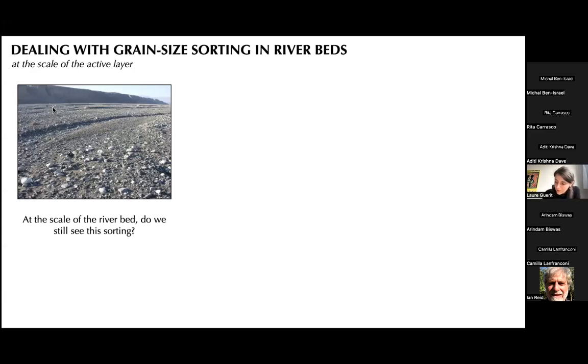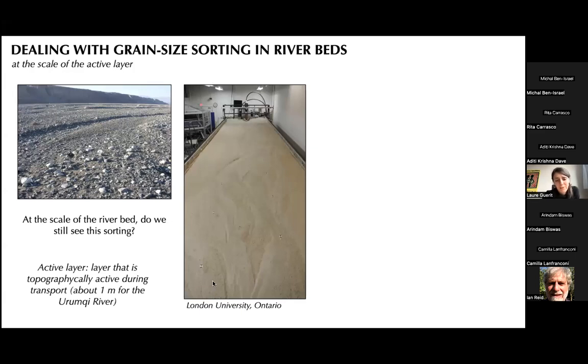To answer this question, we were a bit influenced by the work done by the group of Peter Ashmore in Canada. They have this big flume that I really like. It is about 15 meters long and a few meters wide, and in these flumes they simulate braided rivers with grain size distribution. Looking at these rivers, they define what they call the morphological active layer, which is, to be a bit simple, the layer that is active during sediment transport and where the grains are constantly reworked. In this experiment, this layer is about 4 centimeters thick, and in the Urumqi River, we observe that it is about 1 meter thick, or deep, if you prefer.